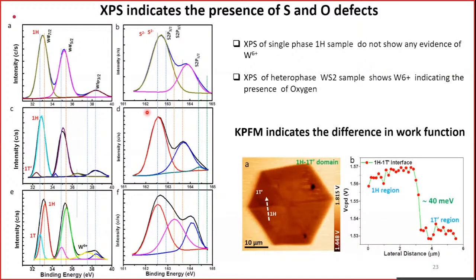microscope imaging. Further, we also connected this to allotropic phase stabilization, because in the literature it is known that the T prime phase cannot be stabilized without any stress or strain, or at least impurity doping. In our case, we found that there is a huge amount of sulfur vacancies, especially in these kinds of biphasic structures. Sulfur vacancies are there, and there is also evidence of tungsten 6+, which means there is also a small amount of oxygen. So the sulfur deficiency and the oxygen incorporation seem to help in stabilizing these kinds of metastable phases.